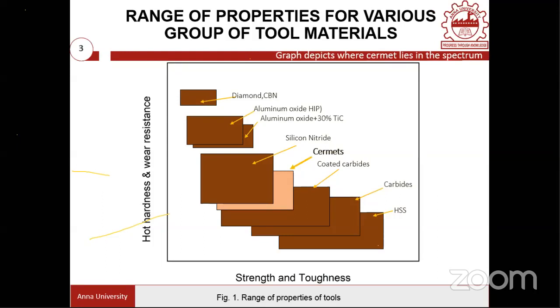And we have an improved version of this cutting tool which is called carbides. We take tungsten carbide, tantalum carbide, and niobium carbide, which are cemented by means of a cobalt binder. And this has good hardness compared to high-speed steel, but the toughness is very poor. And to overcome the hardness problem, coated carbides are nowadays employed. But again, while machining steels and cast iron, these tools face a lot of problems, and wear resistance is one of the challenges in the carbide cutting tool.